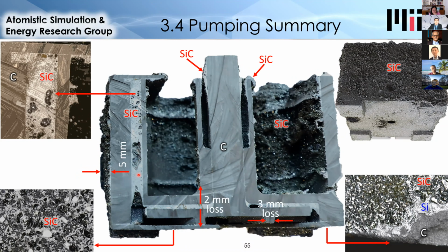And so what was happening here was the same problem we saw in the non-isothermal circulation experiments, where the hotter section at the bottom of the pump was dissolving. Multiple millimeters of material loss was observed on the pump impeller, and then depositing in the colder regions. So not only was the pump dissolving, but it stopped functioning even sooner because the outlet was clogged.